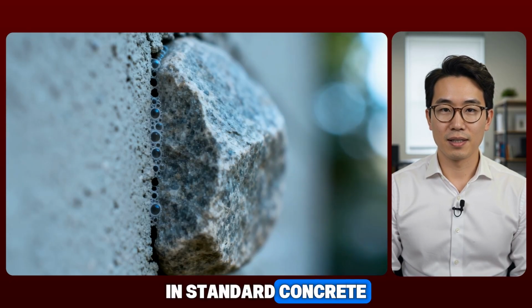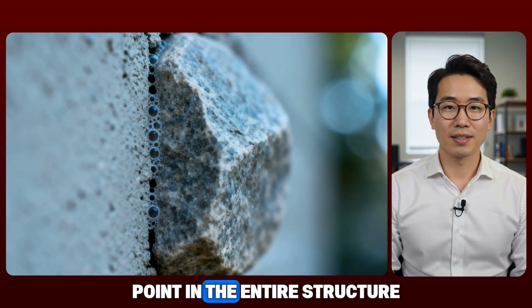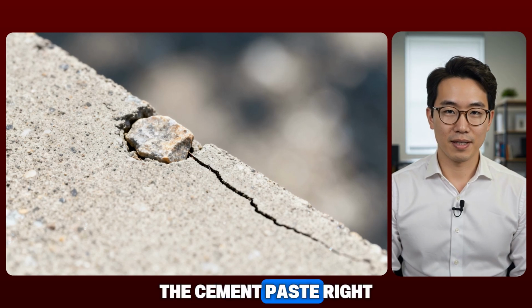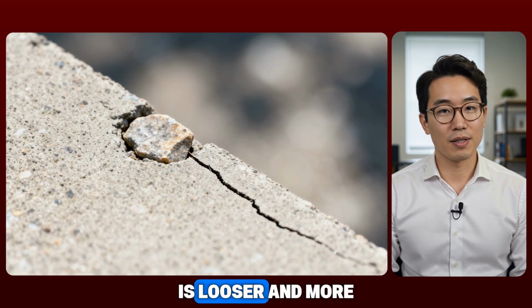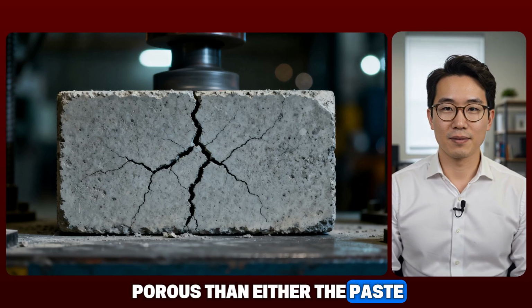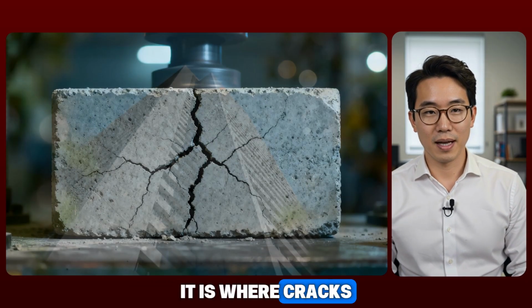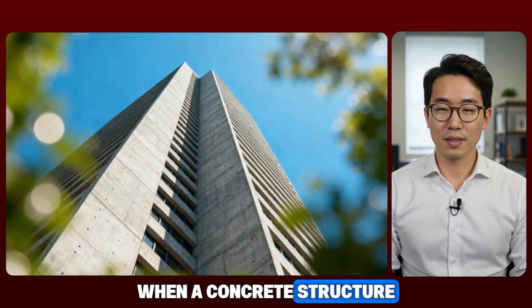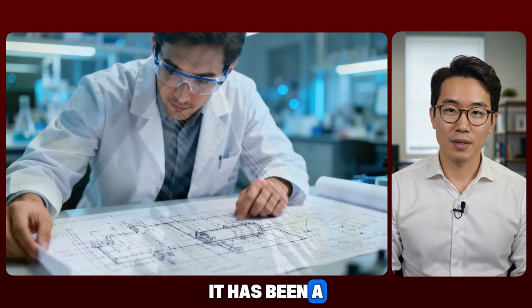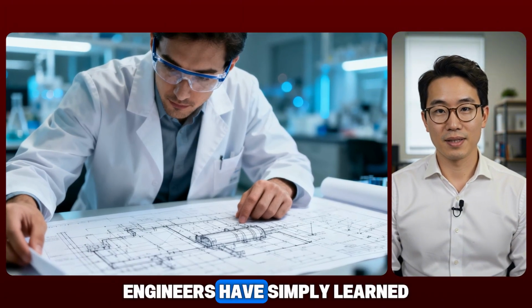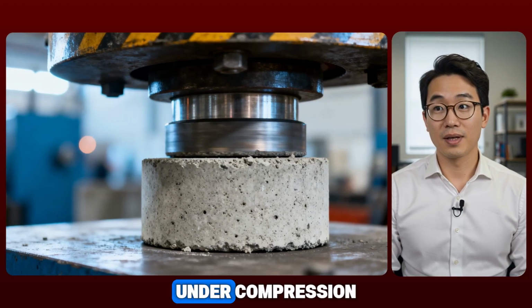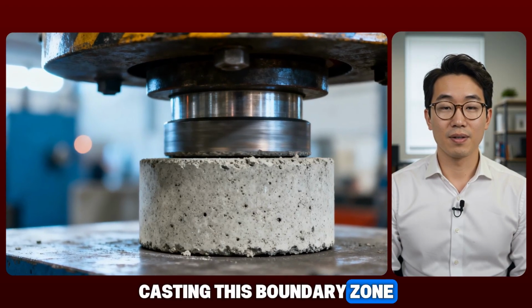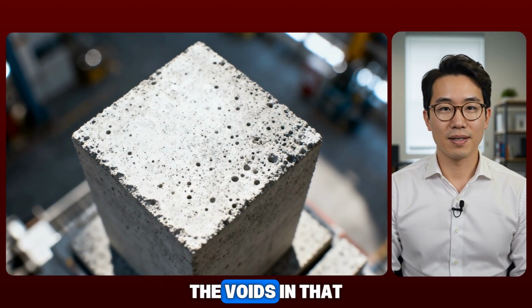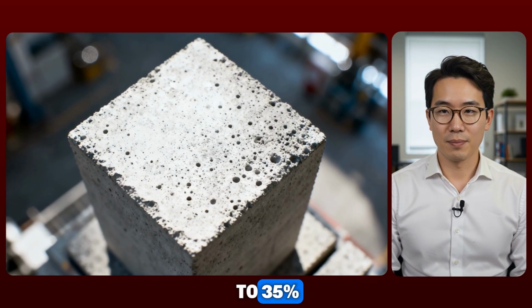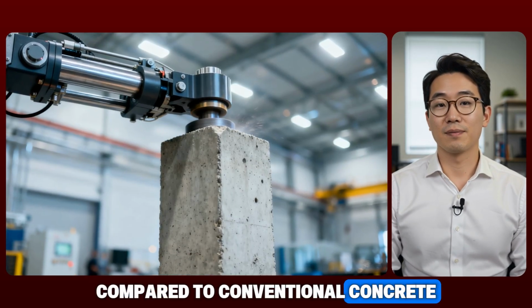In standard concrete, this boundary is actually the weakest point in the entire structure. The cement paste right at that interface is looser and more porous than either the paste or the stone on their own. It is where cracks almost always begin when a concrete structure is under stress. It has been a known vulnerability for decades. Engineers have simply learned to design around it. Under compression casting, this boundary zone tightened significantly. The voids in that interface dropped by up to 35% compared to conventional concrete. The weakest link in the chain got measurably stronger.